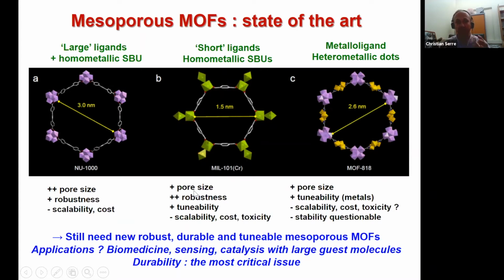When you have very large ligands in MOF chemistry, in some cases, when you remove the solvent, the structure collapses. When you use short ligands, the risk is lower. But here it is made with chromium, so chromium is not safe in terms of toxicity, so it has some side effect. And then the synthesis conditions are quite drastic, so it's difficult to scale up this material.